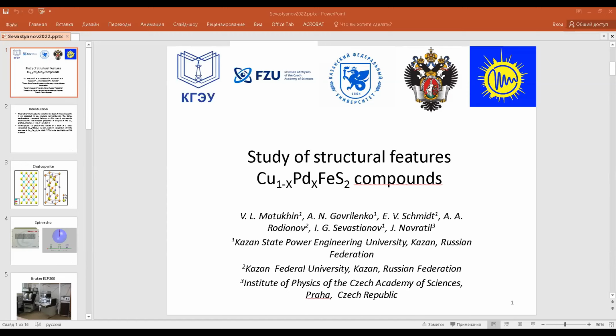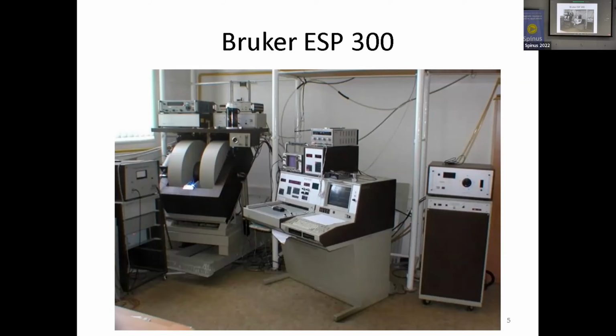Semiconducting chalcopyrite with a tetragonal structure has been recently studied as a potential candidate for thermoelectric application. In the present study, palladium substitution for copper was designed in terms of thermoelectric properties. A series of undoped chalcopyrite and palladium doped chalcopyrite were synthesized. The thermoelectric and transport properties of hot pressed samples were characterized before.